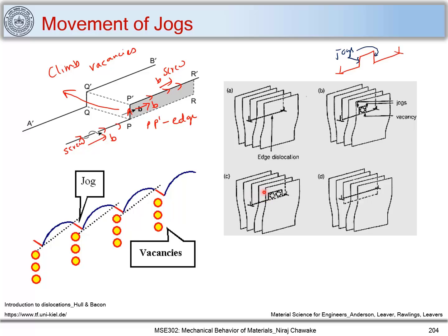So the dislocation climbs up, and we have seen this scenario when the vacancy joins an extra half plane, the dislocation can climb up. And when this vacancy joins this extra half plane, there is a formation of jogs. As I mentioned, the jogs can move by the climb process, and this involves accumulation or annihilation of vacancies.